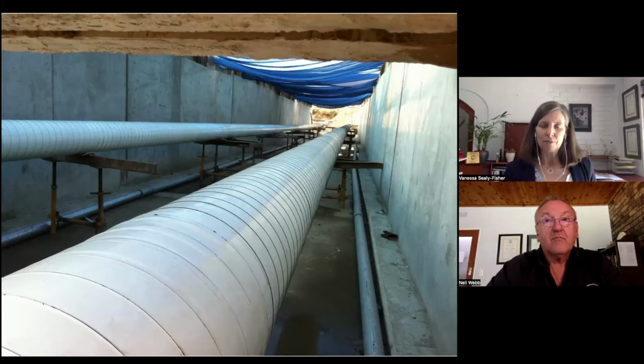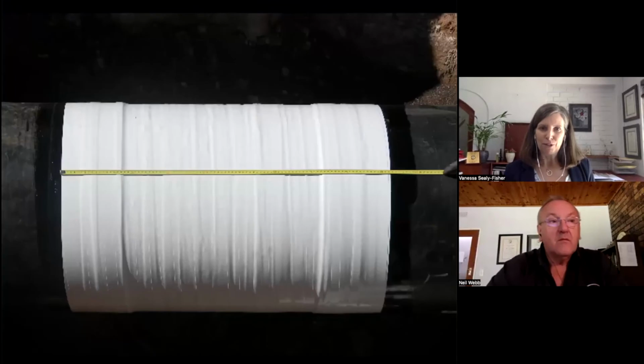I know one of the uses for tape wrapping with which most of the people here today are going to be most familiar will be with field joints. And if we think about field joints, we can see that it's a very practical, relatively easy to apply system, and also a little less stringent in terms of its surface preparation compared with some of the other coatings we've spoken about. Provided the pipe has at some stage in its history been blast cleaned to remove mill scale, then wire brushing is an acceptable surface preparation for most of the tape systems.